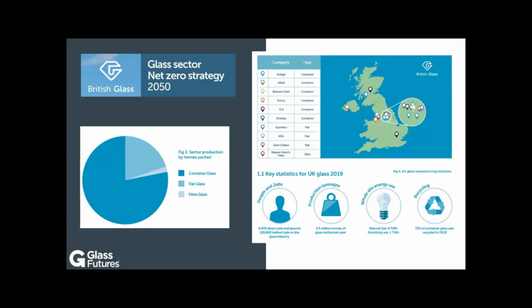Interestingly, if you look at this map, it shows where all the major glass manufacturing sites are. And they're really concentrated along the M62 corridor, mostly in Yorkshire, but also a few on the other side of the Pennines. Apparently that's because of the combination of really good coal reserves and lots of the right quality sand. You can't just use any sand for glass. You have to use quite high quality sand. Apparently, historically, there was lots of that sand available. So interestingly, that's where all the glass is around. So we are really in the capital of glass.